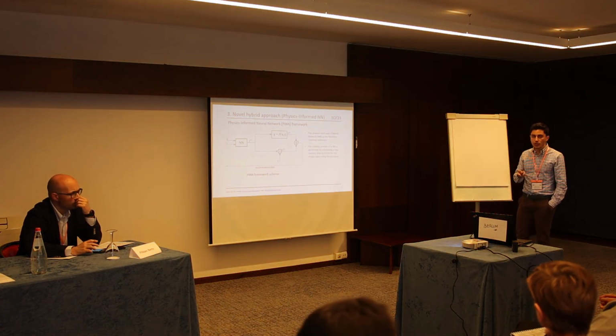right? So the approach that I propose here is essentially physics-informed machine learning. Now I refer to a neural network, but it can be extended to other types of machine learning. Basically, we provide some inputs to a black box, I would say, and then we get an output. This output must be correlated to the actual value, the value that we measure experimentally. And the peculiarity of the physics-informed neural network is that we apply a further constraint to the model, which is essentially this function that tells you that, look, this is your prediction, but this prediction must obey a certain law. It's a law that comes from phenomenological or semi-empirical models.